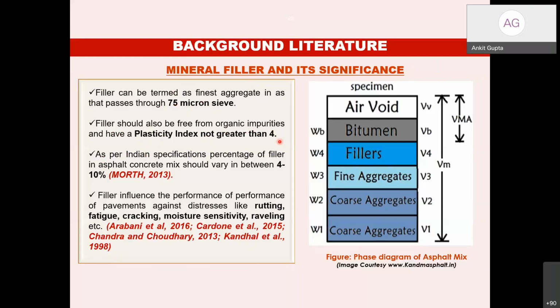Obviously, these two properties are not very self-sufficient, which we have found out from our research also. And we have found out that PI less than 4 is not a very good criterion. The filler should be free from organic impurities, that is a good criterion, but PI less than 4 probably is not. We have our own logic and our own justifications for why it is not.